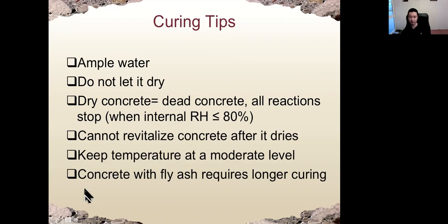Also, the time of moisture curing should be long enough, at least 5 to 7 days.